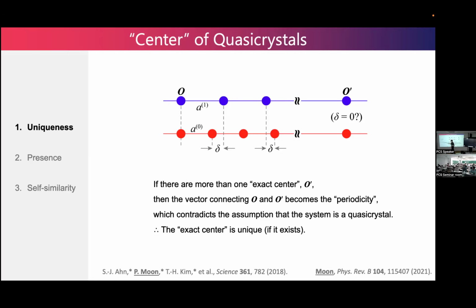This is a sample tiling. Am I right? The center, yeah. There is some rule that if delta is less than some delta C, two hexagons, if you somehow move it, it's a self-similarity. Because of this, uniqueness is simple. Existence was a little confusing, but because of the self-similarity, we could skip existence in this paper. But let's talk about uniqueness. The proof of uniqueness is simple. Use a schematic structure. The first layer has a lattice constant of A1, and the second layer has A0. And delta is the local in-plane displacement between layer 0 and layer 1.